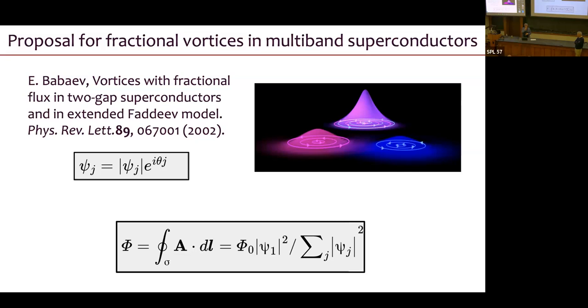And what we found is that these vortices, the baby vortices, the fractional vortices, could be many penetration depths away from any other vortex. So that's the part that makes it plausible, and that's the part that's hard to explain in any model other than the Babaev model.